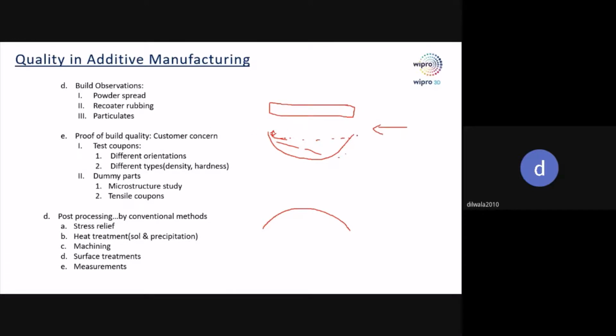So the operator has to observe carefully whether the powder is spread properly, at least for the first layer. From there, later on, the machine ensures the layer thickness. At least for the initial layer, the operator has to ensure that there are no gaps like this on the build plate and the powder is properly spread. In this case, when the recoater moves this way, powder would be filled here, and there will be no powder to melt here. So the operator's observation becomes very keen here.